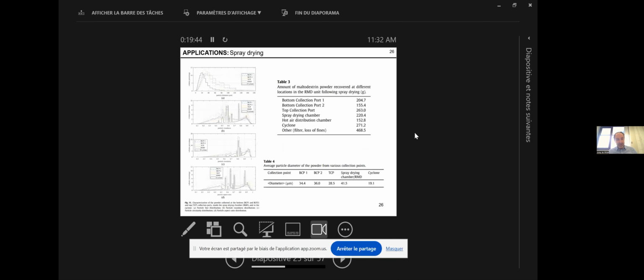We have microscopic analysis. Some we went too low in vacuum, so the particles exploded, they fragmented, but under the normal microscope you can see that we have quite spherical, hollow particles produced. And then we do all the analysis on those particles that you are familiar with. We do particle size distribution measurements, roundness distribution measurements, and so on.